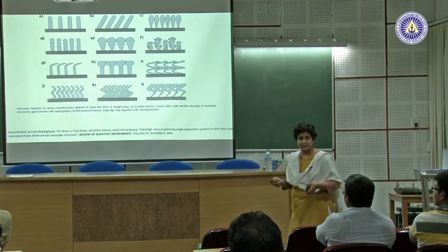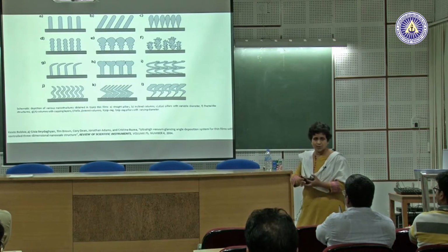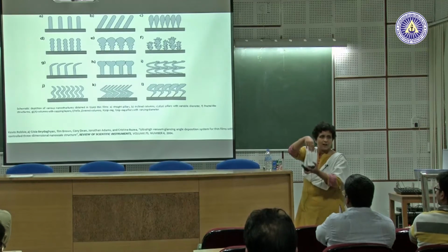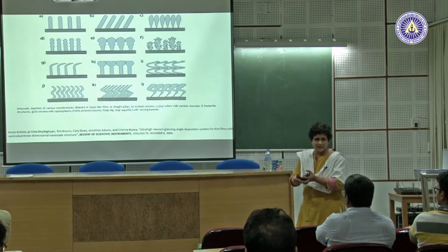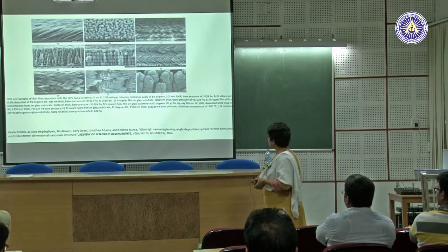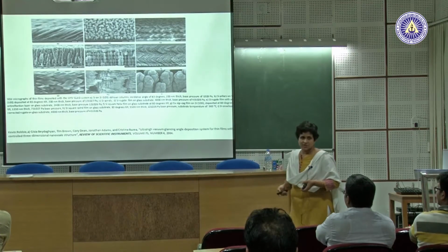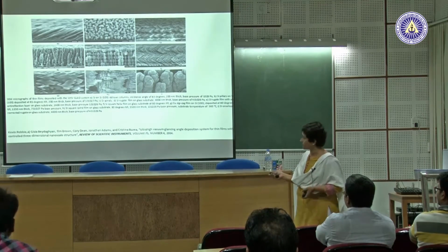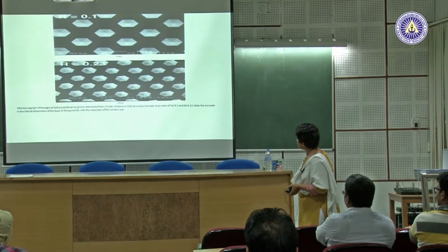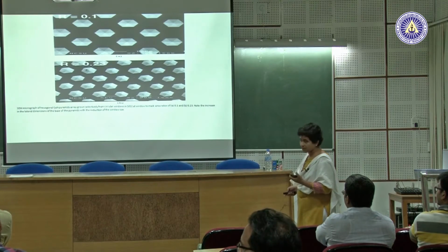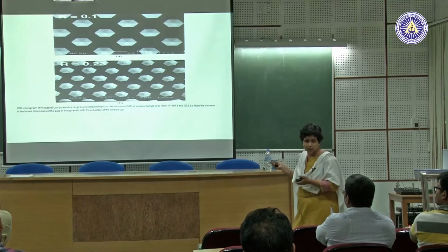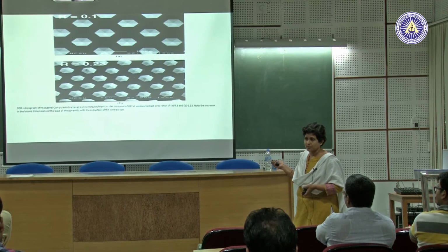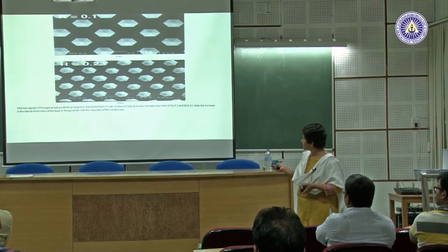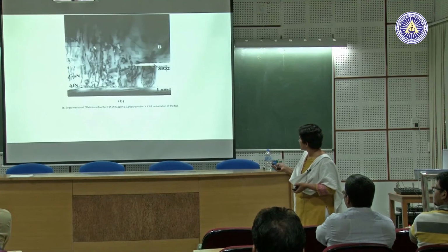Yes. So, you can make this from thin film deposition by controlling the direction at which the species are coming, how they are getting deposited, and then by rotating it in the right way. Okay, so, that is very beautiful. These are all real images created by thermal evaporation and controlling it. If you are controlling the crystallinity, you can actually control the shape of what you are depositing. Very nice hexagonal shapes can be created.